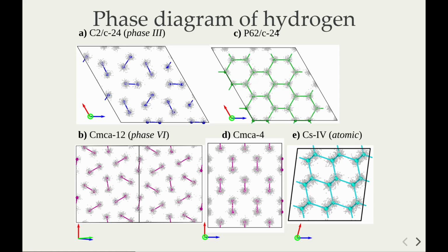Now these are a few candidates which have been identified mainly by the work of Chris Pickard in past years. Here you can see that the big balls in the center are the average position of ions, while the small dots represent the quantum fluctuations of ions at 0 Kelvin. So these are snapshots extracted from the quantum simulation of actually where the ions are, even at 0 Kelvin. You can see that the quantum fluctuations in this system are really sizable, comparable with the bonding distance.